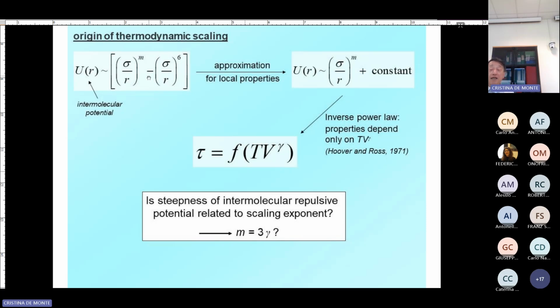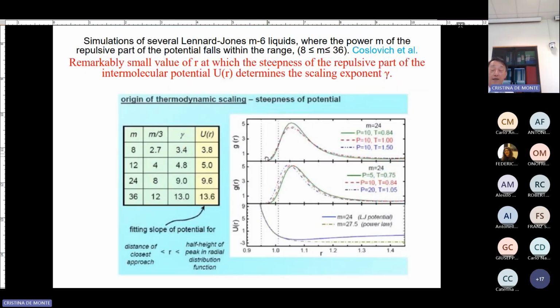But even so, with the attractive part there, it's pretty close to this prediction, because somehow this is determining this relation. I'll tell you why. This is the potential now for this Lennard-Jones system. It turns out that gamma is determined at very short distance. This is g(r), the structure factor, as a function of distance r. And this is the potential that is used in this simulation here.